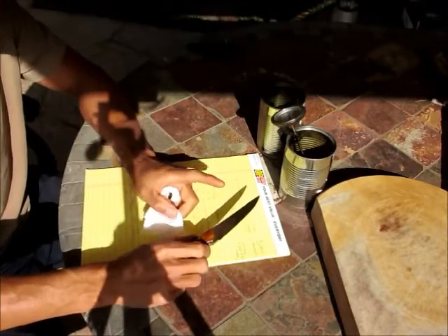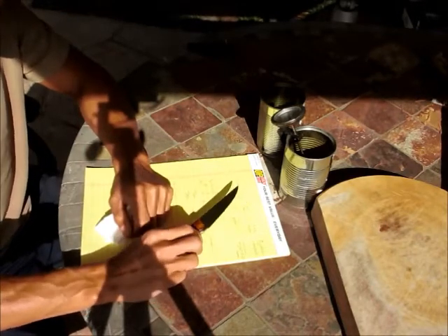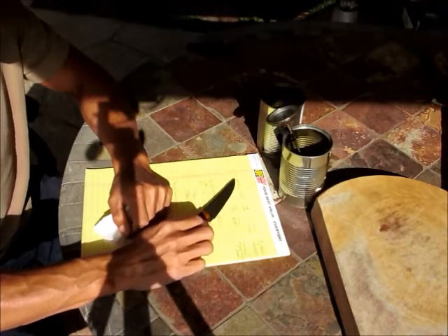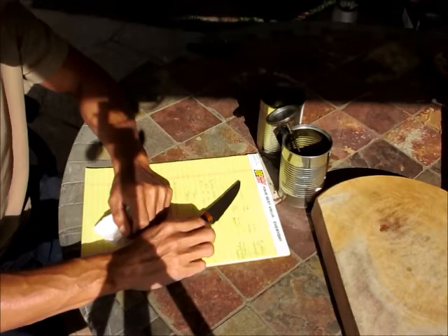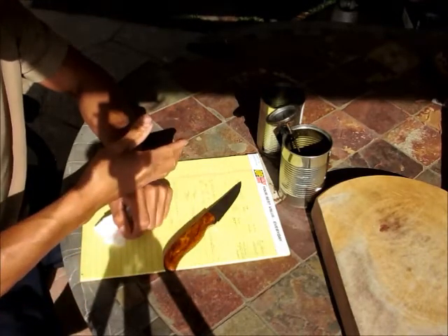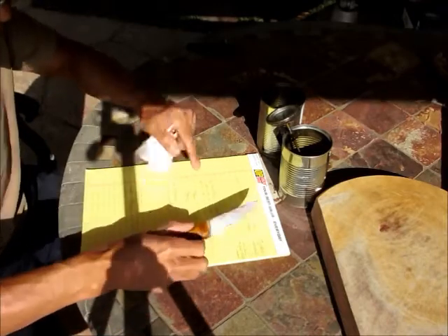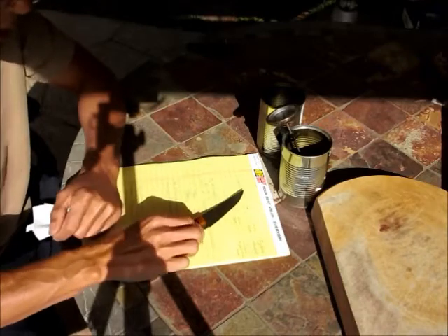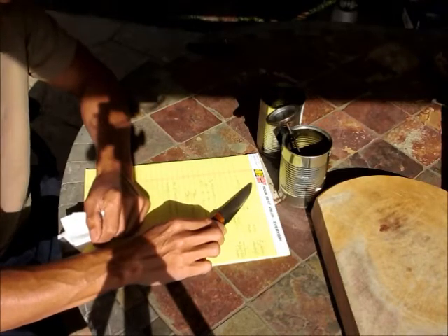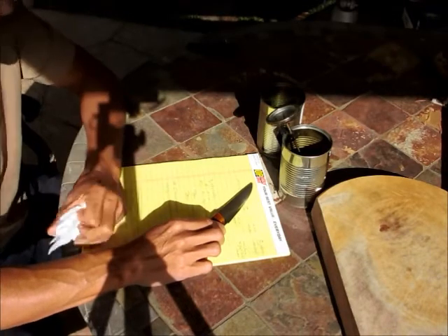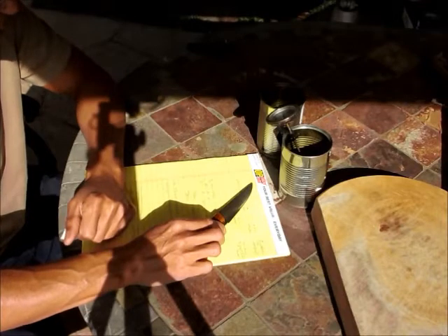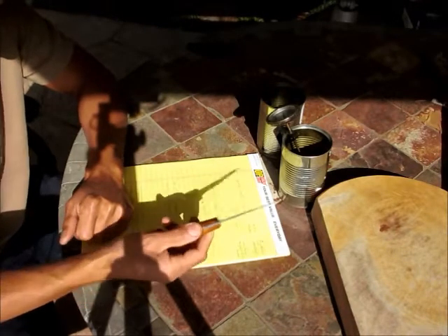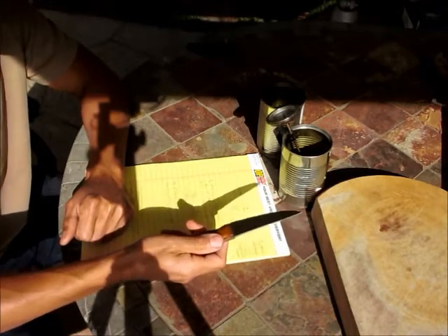Do it two to three times. Your blade is going to drop about half a Rockwell, or up to 1.5, depending on the type of metal. Because this steel is so high alloy, it doesn't drop that much. But if you have lower alloy and lower carbon, it will drop more. So you drop between about half a Rockwell to 1.5, going from, say in this case, 310, 315 Fahrenheit to 350 to 375, or you can go all the way to 400 Fahrenheit, about 205 Celsius. It doesn't really matter, and it's not going to ruin anything.